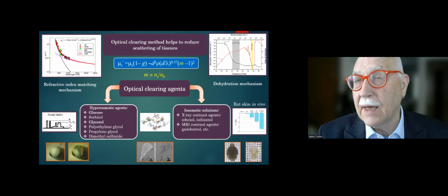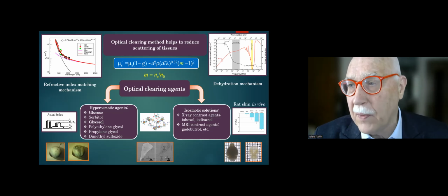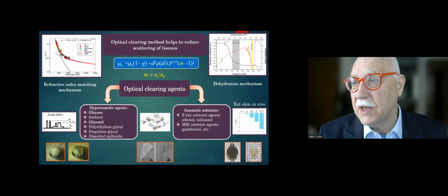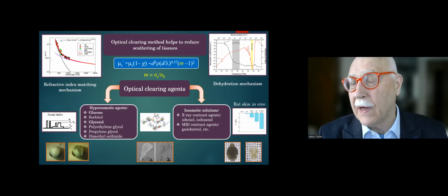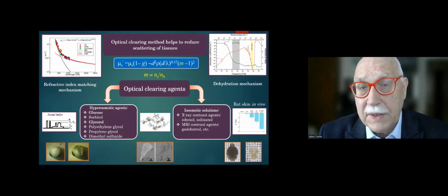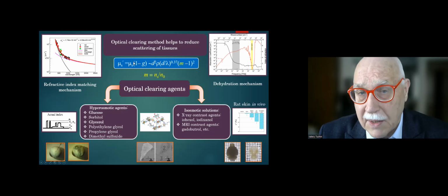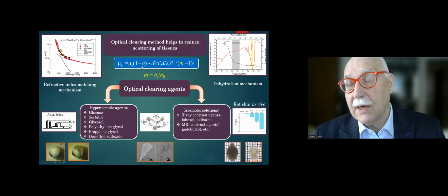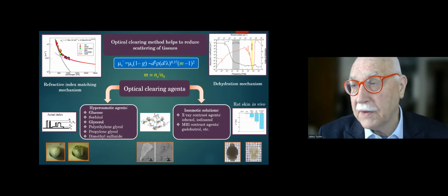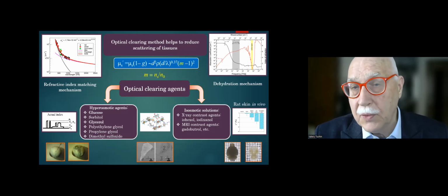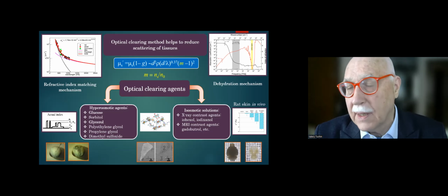Indeed, absorption and scattering can enhance each other, because if you have a longer pathway for photons in absorbing or slightly absorbing media, like in tissues, this absorption is enhanced due to longer pathways of the photons which are traveling within this tissue. How to describe it? In the framework of the Mie theory, you can write a simple equation for the reduced scattering coefficient, which depends on the real scattering coefficient and the anisotropy factor of the scattering. So the anisotropy factor shows us how a photon travels after a single individual scattering. And for many soft tissues, the factor is close to 0.9. So this is highly anisotropic scattering.